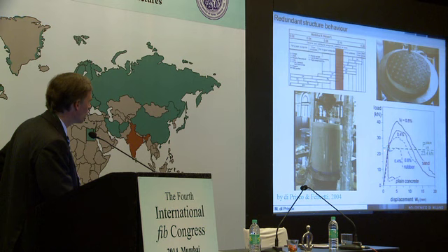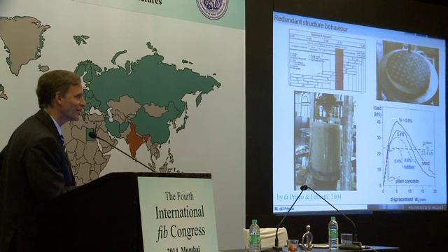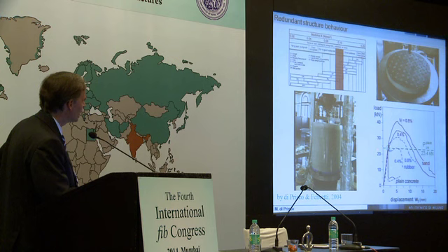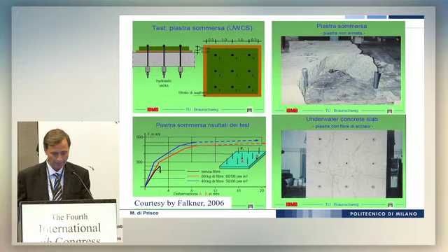And you see that with plain concrete, you have a very brittle response because the size of the plate is small. But if you have a redundant structure, so you have a soil, and especially you introduce fibers, you can have with 30 or 60 kilograms a very ductile response with also a hardening.